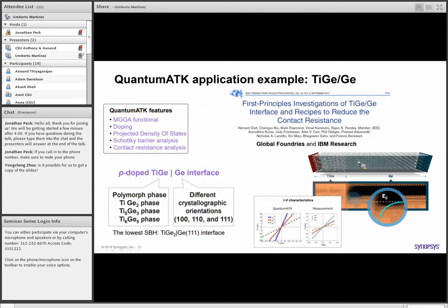So by using exactly these methods, I just want to mention this application, this paper that has been published, because they really show, for example, this work where they studied titanium-germanium interfaces, the study done by GlobalFoundries and IBM Research. They really wanted to understand, by changing the phase of the titanium-germanium polymorph and the crystallographic orientation of the germanium phase, what's the best combination that gives you the lowest Schottky barrier height. And they finally found that this would be the right combination.